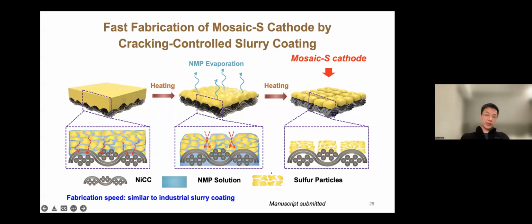On the cathode side, sulfur cathode, of course, we also have a big headache because we need to coat a thick sulfur on top of the current collector, right? Normally what we get is that if you buy from the market, a thick one always performs very poorly. It will give you 700 milliampere hour per gram, something like that, or 800. That means thick sulfur does not give you good performance. For those papers that publish many strategies to coat thick sulfur, it typically, again, takes a very long time.